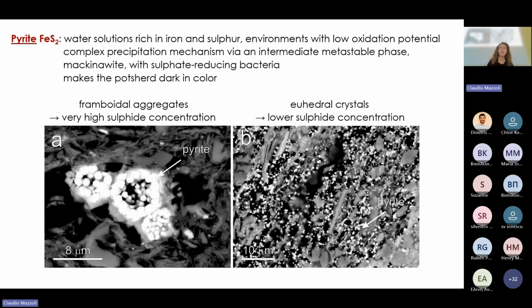This secondary calcite precipitated underwater. Another phase that you can meet during the analysis of materials from underwater sites is pyrite, which can form from different mechanisms. It's a very complex crystallization process, and it depends a lot on the environment, especially on the quantity of sulfur that we have in the environment. We can have pyrite forming framboidal aggregates, which record very high sulfide concentration, or euhedral crystals, which record low sulfide concentration. The shape reflects the concentration of these compounds, so it provides us information also on the type of environment.